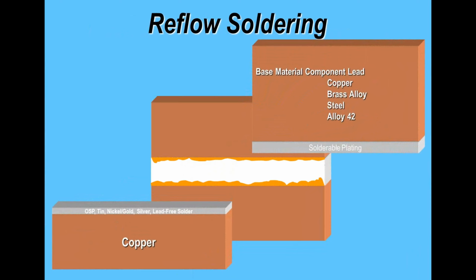When we look at the component terminations, we're either soldering to copper, again, brass alloy, steel, or alloy 42. Those are the most common termination materials, with the exception of chip components, which may be a silver or silver palladium termination. Now, copper is often used as a barrier layer on certain components to aid soldering and wettability, and then a tin coating is put over the surface. As an example, alloy 42 and steel and possibly brass may have a copper plate underneath the tin to allow you to solder to those surfaces more effectively.